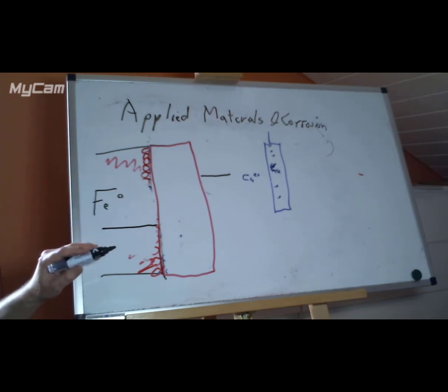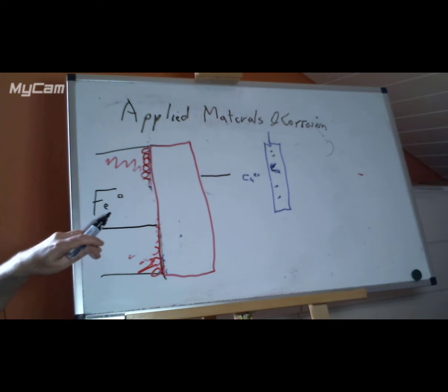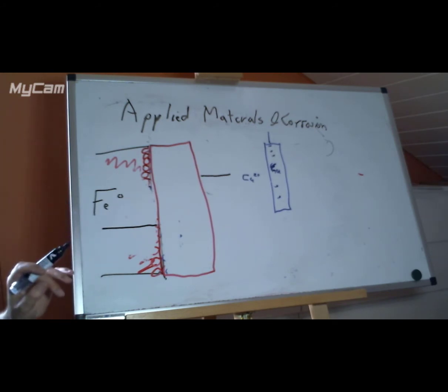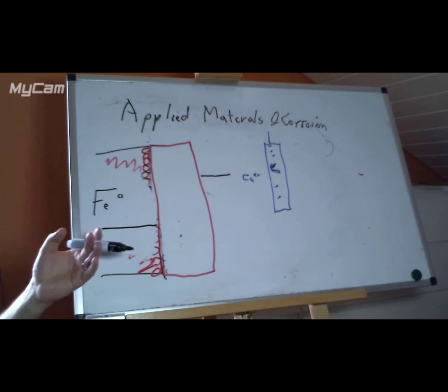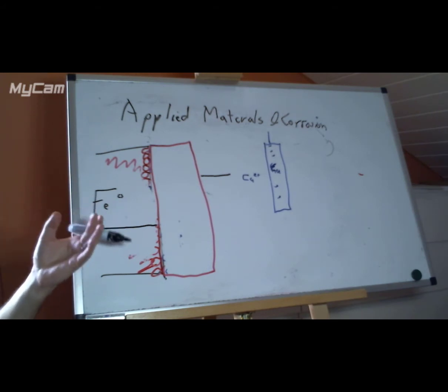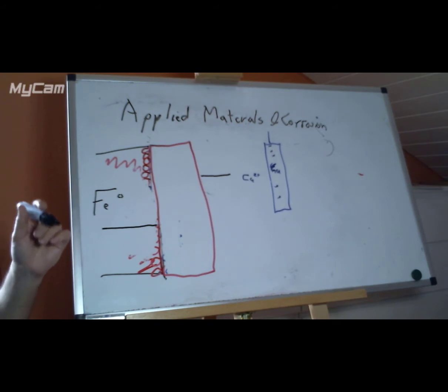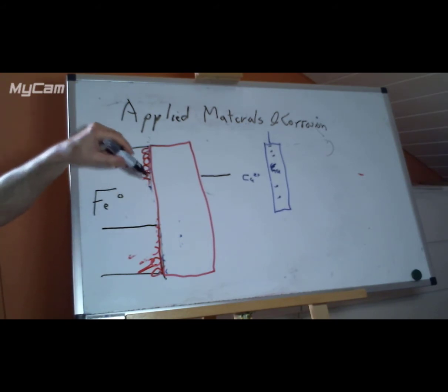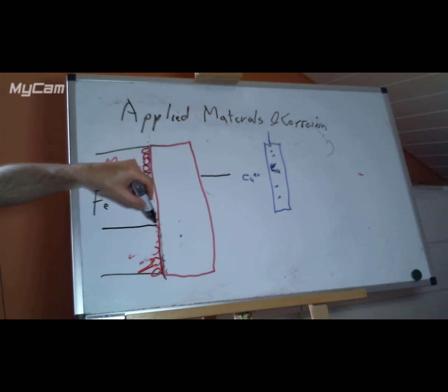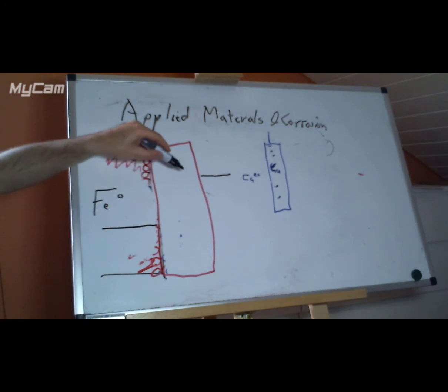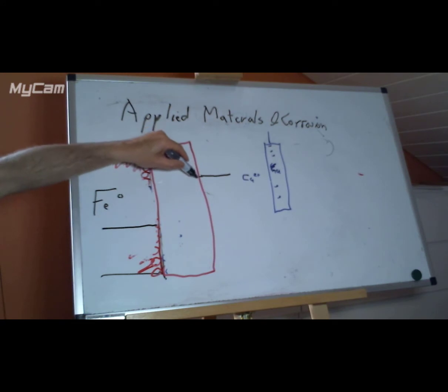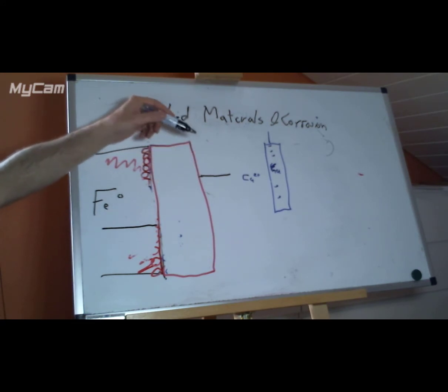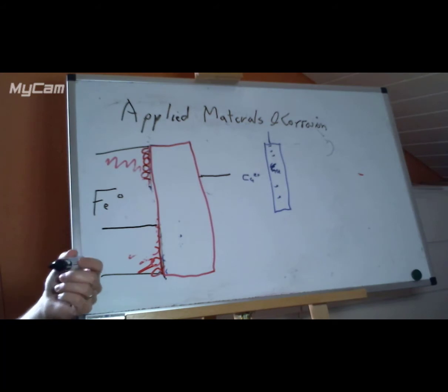We will get onto the different types of oxides in a bit, so we will think of it first of all as a single oxide, just one particular type. The problem with iron is it has several oxides, so they don't behave quite the same. But let's first of all imagine that it's got one. So something like aluminium has a single oxide layer that has just one chemical formula, and it's very resistive. So then we would expect a single resistivity, and the resistivity is not just to electrons, it's also to ions.